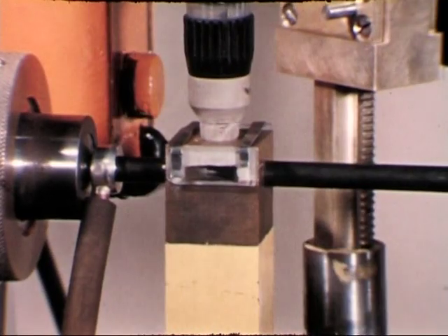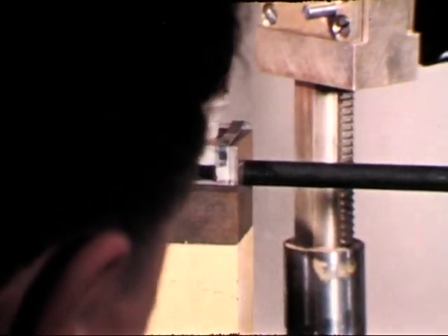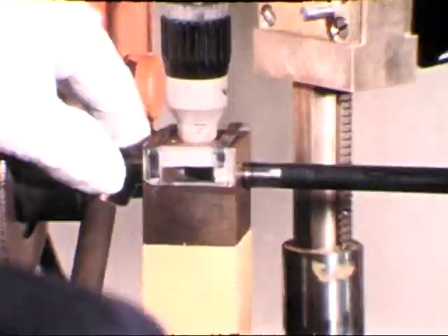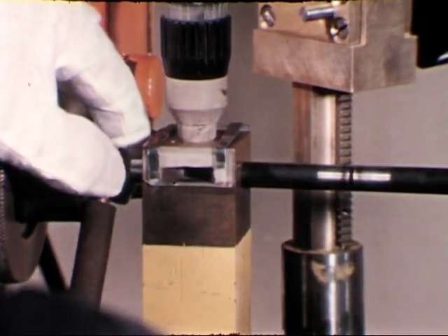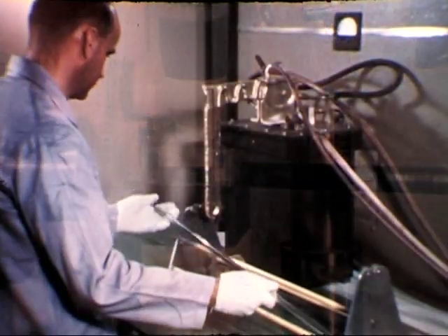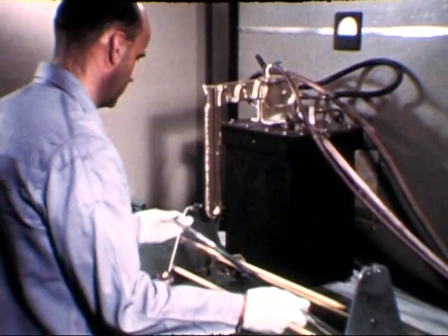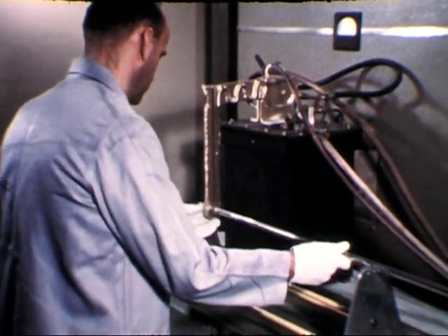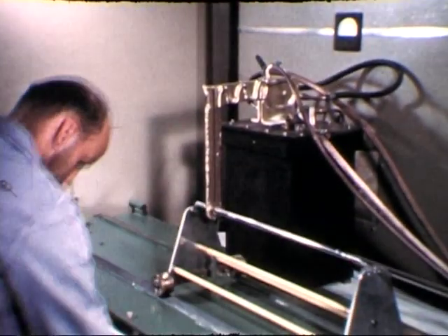Chill and gas retainers surround the electrode and weld area. Welding is purposely limited to the 20 mil zircaloy cladding and is made in a double pass, each pass requiring a different welding current. A section bond is made at each weld by fusing the metal in a small zone to add mechanical strength.